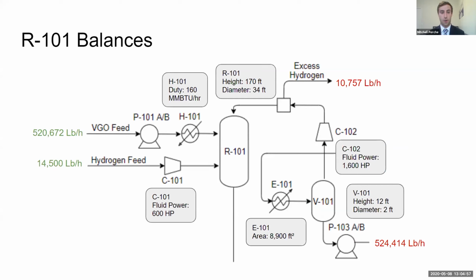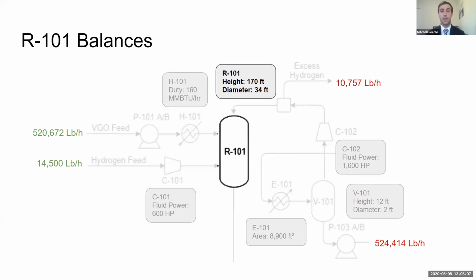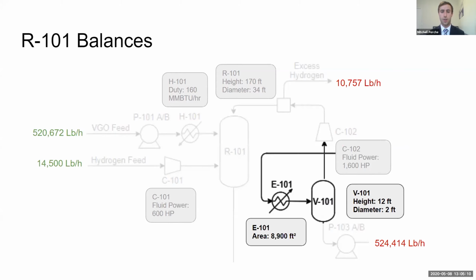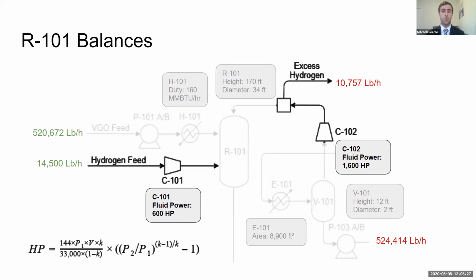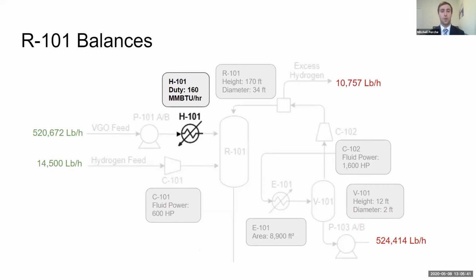Taking a look at our reactor section of our unit, we can see here that we have a mass balance that does seem to check out. Our reactor, R101, has a height of 170 feet and a diameter of 34 feet. The product stream of our reactor is being sent to E101, where it is reduced in temperature, which allows for easier flash of hydrogen, where we're able to recycle this hydrogen and pressurize it back up using a compressor. We size the compressors based on this equation on the left, where we have an inlet and outlet pressure chosen with a volumetric flow rate and a K constant. Another key takeaway here is our heater, which allows us to heat up our VGO feed to reactor conditions.